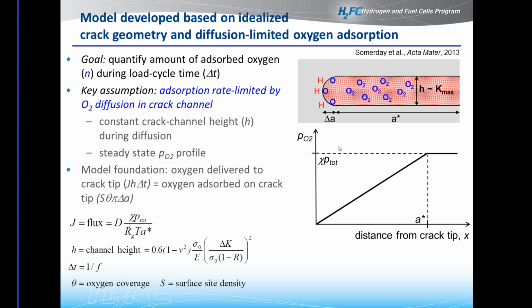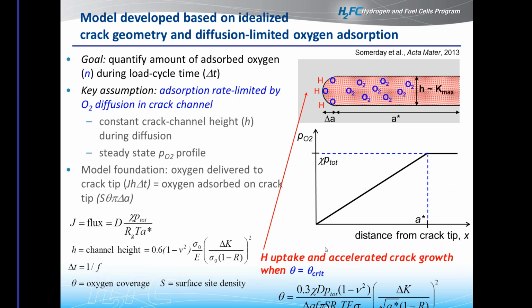So without getting too far into the details, really it's just a matter of the flux of this competition, really, of oxygen getting to the crack site and it being able to adsorb. And so the model really is reflected in this equation in the bottom right corner. And what it's really telling us is that hydrogen uptake and accelerated fatigue crack growth will occur when oxygen coverage is not sufficient to fully passivate the surface. So we applied this to this X52, and I'm not going to really show how the correlation occurred, but it actually showed some pretty good correlation. So all these variables can really be modeled and really help the possibility of mitigating the effects of hydrogen embrittlement.